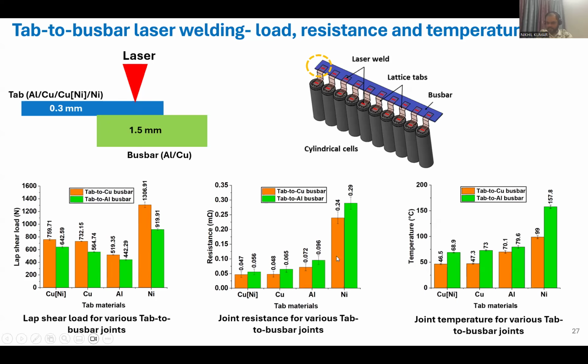And in this middle one, this is the resistance comparison. What I have seen, the lowest resistance is achieved for the nickel plated copper and maximum resistance for the nickel. Similarly for the temperature, as the resistance is lowest for the nickel plated copper, the lowest temperature is also for the nickel plated copper. So I think this is showing a similar trend to the previous slide, what I have shown for the tab to the cell, but the only difference is here I have used different busbar materials, aluminum and copper. So I think this is a very useful slide. If you are doing any DOE study or some comparison, you will have to consider these three characteristics, strength, resistance, and temperature, for deciding which is the best tab material.